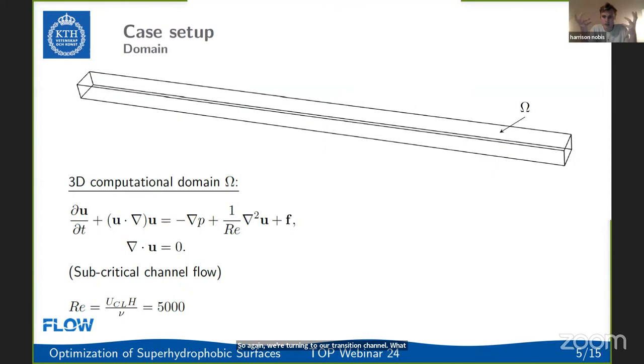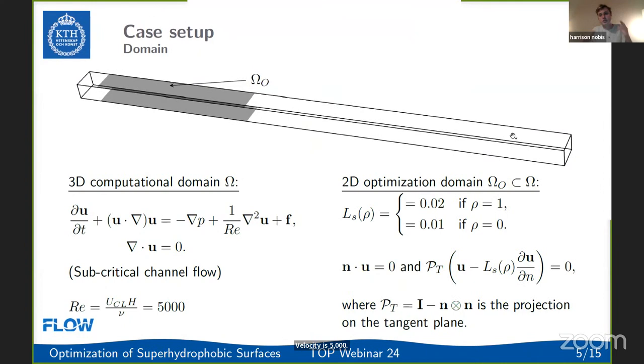And our Reynolds number based on the half channel height and equivalent centerline velocity is 5,000 here. So we're looking at subcritical transition. But we also have this 2D optimization domain on the top and bottom surfaces where we can paint our two different superhydrophobic paints, right? And these two numbers that we've chosen for the slip lengths are arbitrary, but arbitrary within reason, in the sense that people have manufactured superhydrophobic surfaces with these slip lengths.